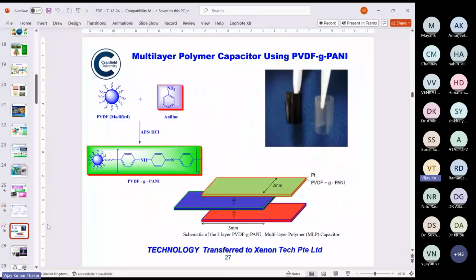So building upon our preliminary work, we came up with the alternative approach of incorporating aniline monomer, and we were able to incorporate it in a very interesting way, where, if we talk about weight percent, we incorporated 12% of polyaniline. But interestingly, it was not that conducting, because if you see some of the research papers, when they add traditional polyaniline, then after 5% of addition, it becomes completely conductive. However, we were able to incorporate it in more of a nano form,